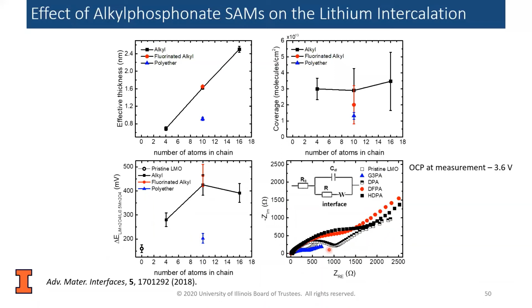If we look at the impedance right here, we see that we'll get the largest amount of impedance from the tallest sample, which is expected. Also, the hexadecyl is a 16 chain length. The fluoroether, the fluorinated alkyl, also has a high impedance, even though the coverage in this isn't as high as the alkyl 16 chain length. Because fluorine is larger, it's harder for the ferrocene to diffuse in and actually interact with the LMO. Then we can see that pretty much the polyether and the pristine LMO look identical.